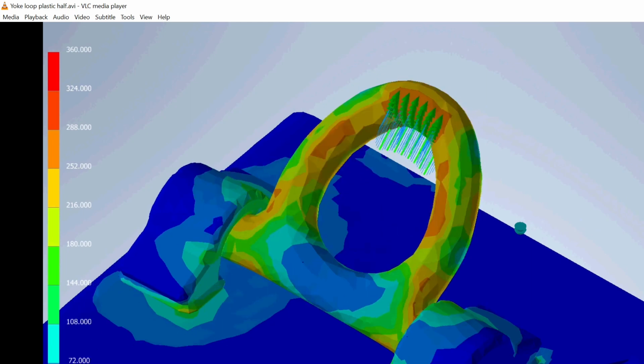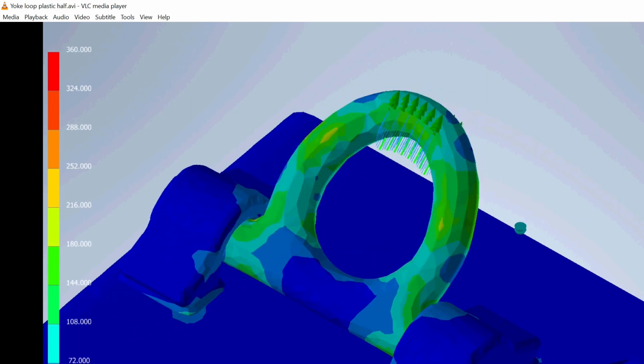And when you reduce the load, the residual stresses are staying behind, so once the load is removed, the plastic deformations leave an uneven stress area behind, which could make the component sensitive to a different loading direction, because these residual stresses will sum up with the next loading cycle in case it's somehow different. And we can see very tiny amounts of residual stresses in the welded connection, which seems to be okay.